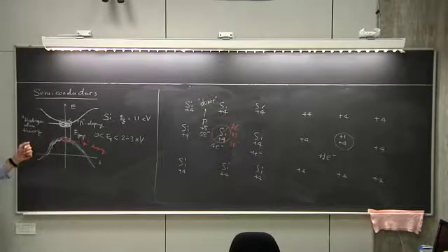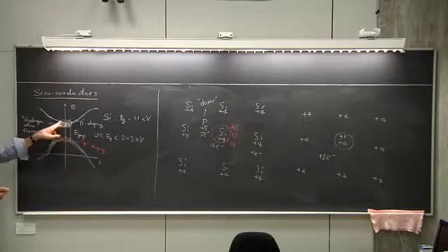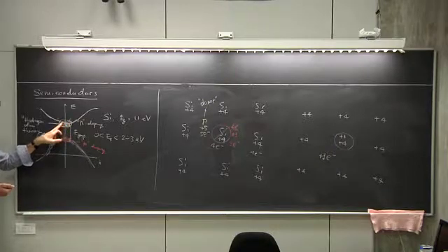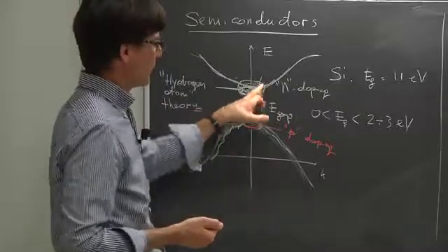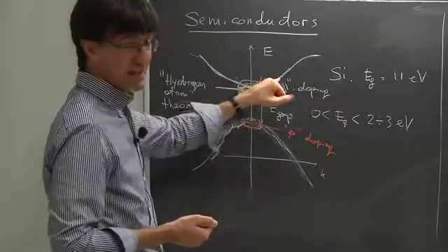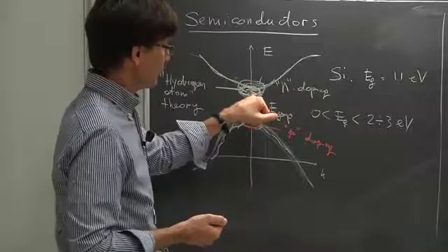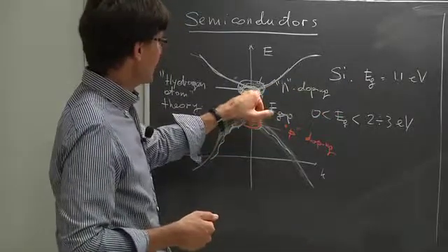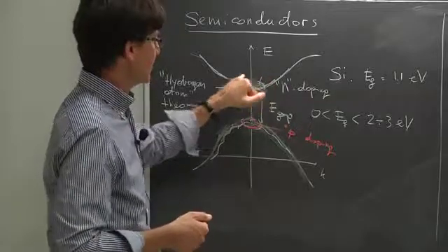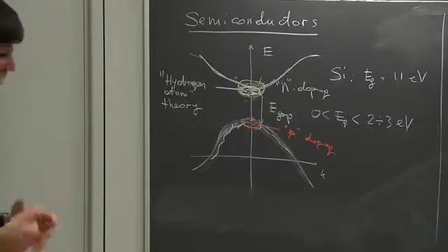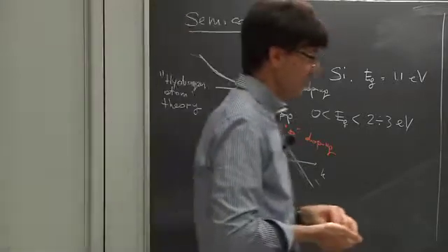At standard temperature conditions, these states are actually empty, because the number of such states is small compared to the number of available states here. Here you have a number of states comparable to the number of unit cells in the system. Here you have a number of states comparable to the number of impurities. So at the end of the day, these electrons will all be excited at standard conditions into the conduction band. So yes, you are introducing additional states, but it's rare.